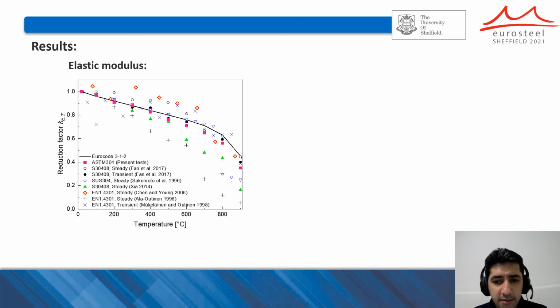Now that we have obtained the material properties, we can discuss and compare the results of the present study with the data already available in the literature. First, elastic modulus, which is the slope of the stress strain curves at the origin. You can see here the results we have obtained for elastic modulus are markedly lower than the predictions by the Eurocode diagram. In general, a significant disparity is observed between the results of the elastic modulus reported by different sources.